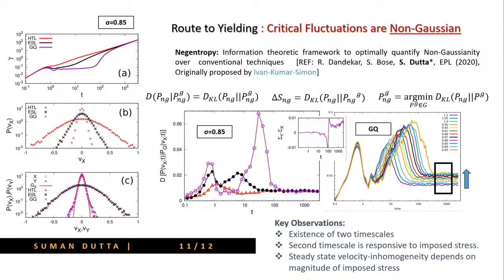And this is the behavior of this non-Gaussian parameter as a function of time for 3 different states. In the GQ case, we are imposing the same stress value on all 3 different levels of glass, and in the end they become identical, as all these different glasses lose their memory, but their transients are very different.